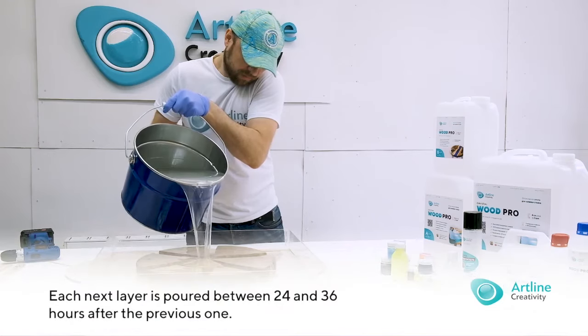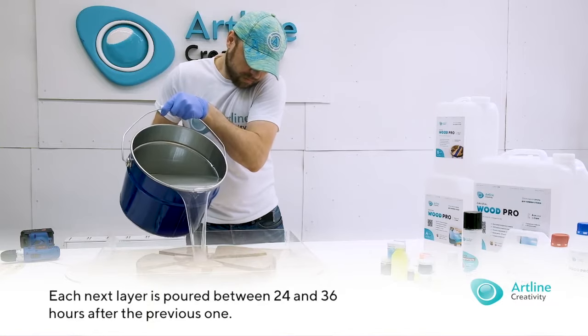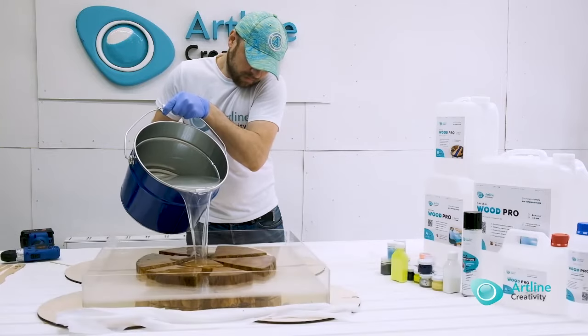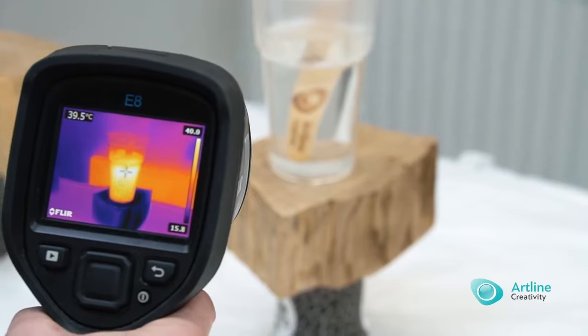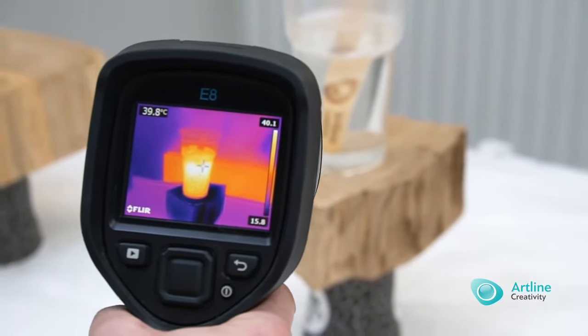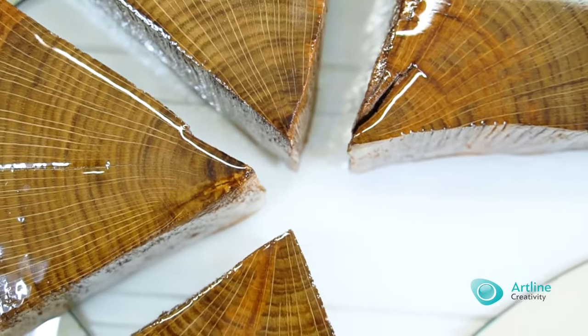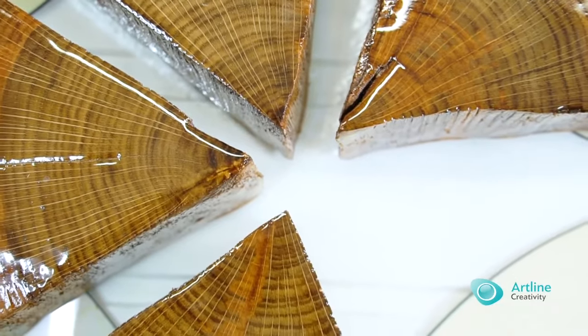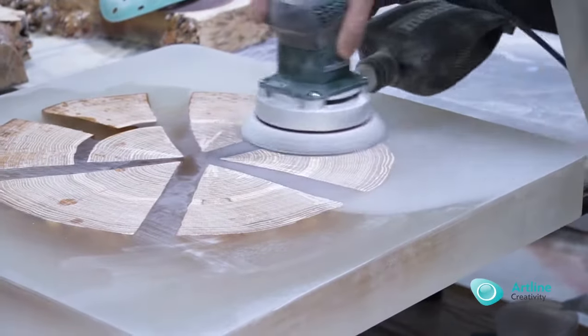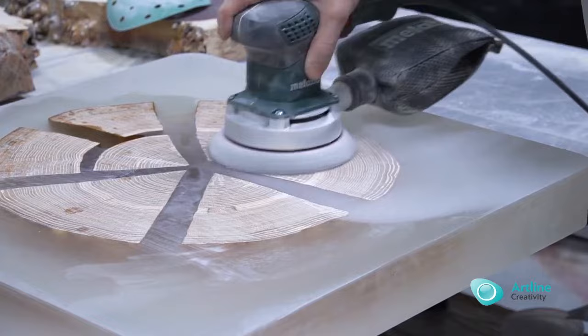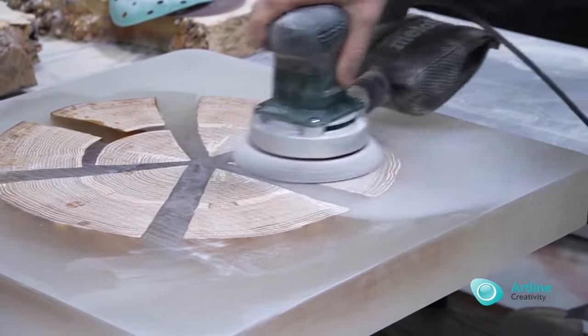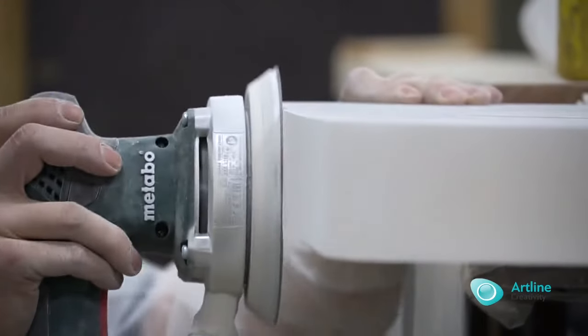If you fill it later than the specified time, the lower layer will harden strongly and will not be able to merge with the upper layer. In this case, you will see a transition between the layers. You can control the casting temperature with a pyrometer or a thermal imaging camera. The next layer can be cast after the layer has cooled down to 30 to 35 degrees.